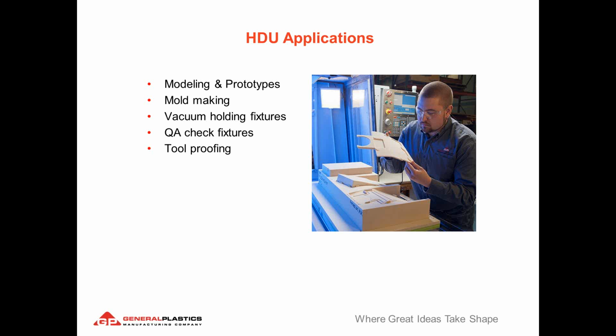That goes into the next option, which is a QA check fixture. You can machine a part and use a QA check fixture to check the dimensional tolerances of your machined part. And also tool proofing. As I mentioned before, foam, especially in the lower densities, is much less expensive than metallic billet. And so we can prove out your tooling programs on foam first before you commit to cutting into metal.